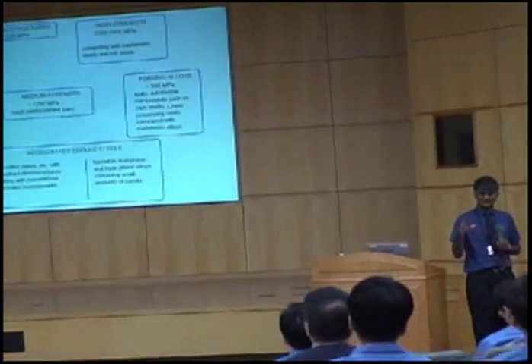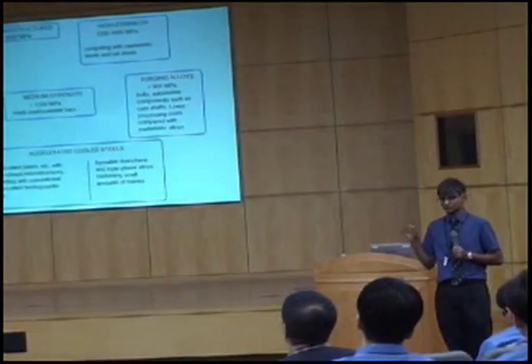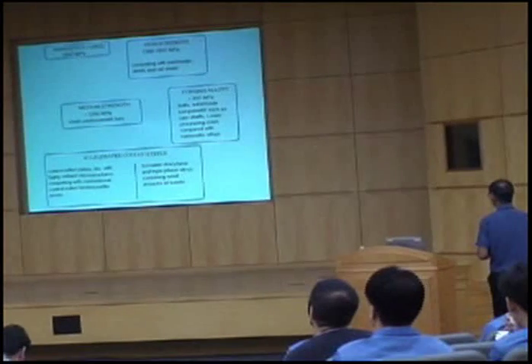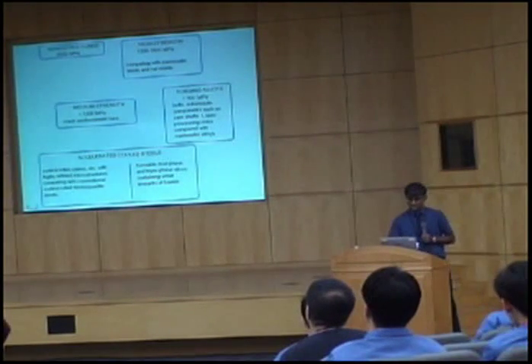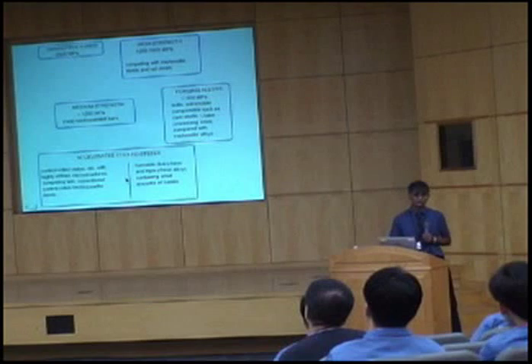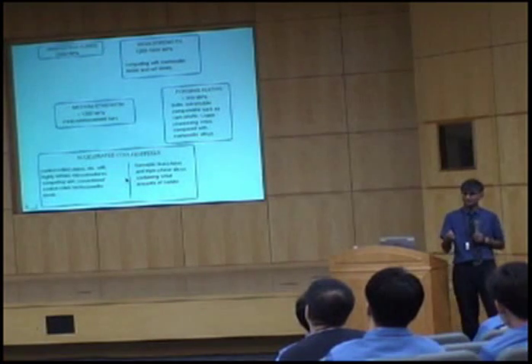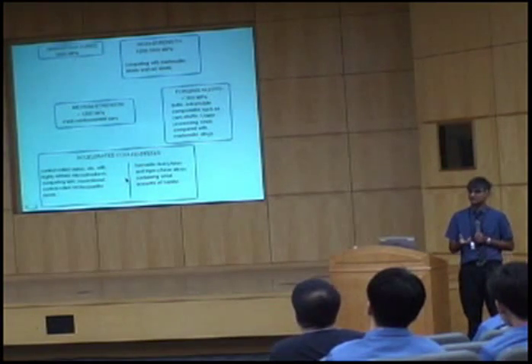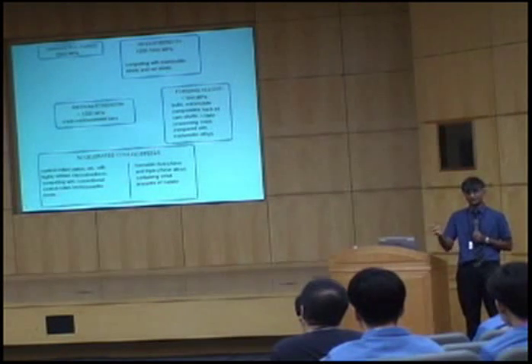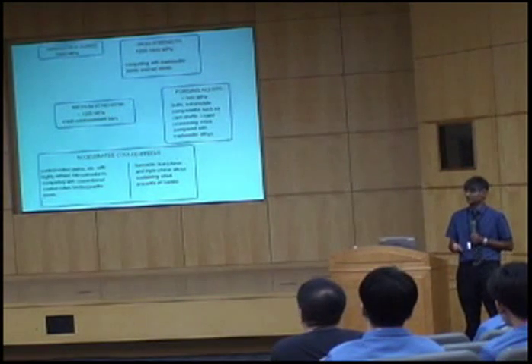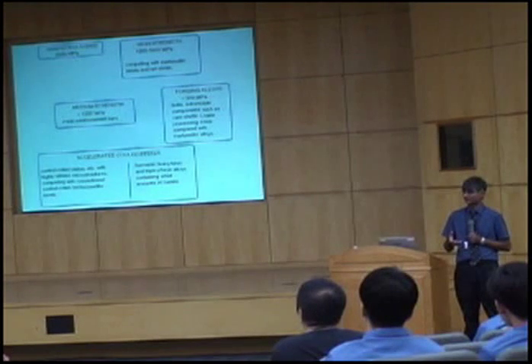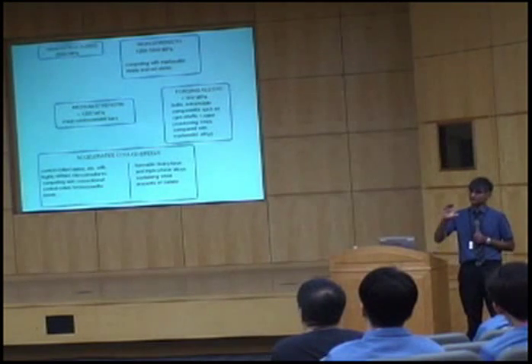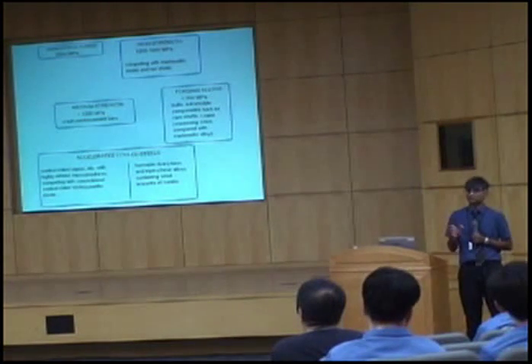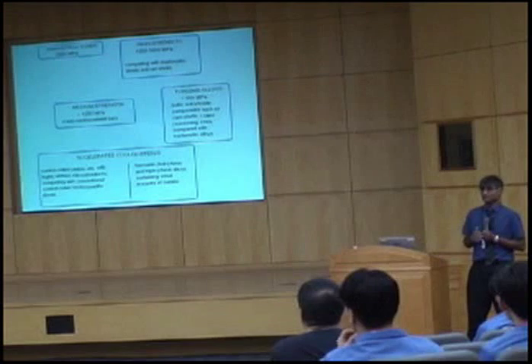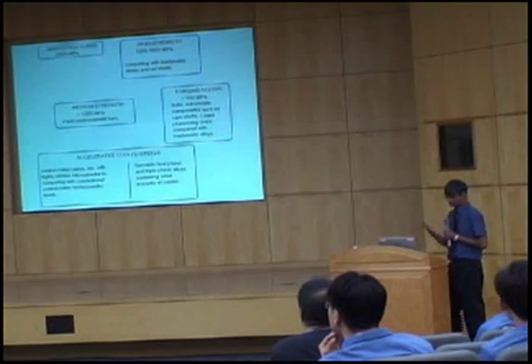Now, there are many kinds of bainitic steels, and I'll just very quickly summarize those steels for you. You are very familiar with accelerated cooled steels, which basically are low-carbon bainitic steels, and you use the high cooling rate to produce the microstructure instead of using lots of alloying elements. And in doing that, you can produce bainite in very thick sections, for example, for shipbuilding and so on, using very few alloying elements and having good weldability.